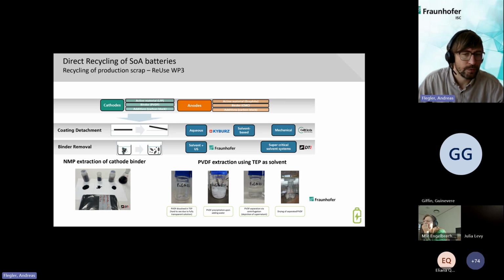Here we start using solvents. The first state-of-the-art process is the extraction of the binder with NMP. It's not the best way, and NMP is not the best solvent to use, but for a baseline, we use this. A very promising solvent is TEP. Here you see in the pictures, we dissolve PVDF as a model system in TEP, and it dissolves very well. Then we put some water in it, and the PVDF precipitates, and we can centrifuge it and separate it from the solution.